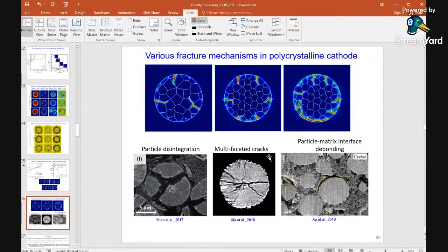Okay, so in the experiment we see the particle disintegration, and we see the multifaceted crack. We see particle-matrix debonding, in different experimental observations. So what we can see is that from our model, we can incorporate experimental or microstructural information, and we can really simulate complex phenomena for any sort of cathode system, and we can directly correlate the fracture process with it. It requires a lot of high-end experimental techniques, and it can be extended to the three-dimensional scenario.